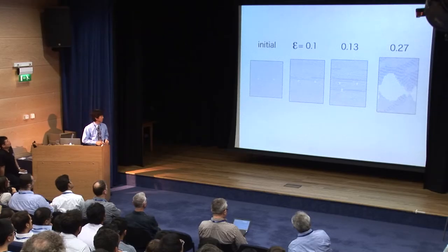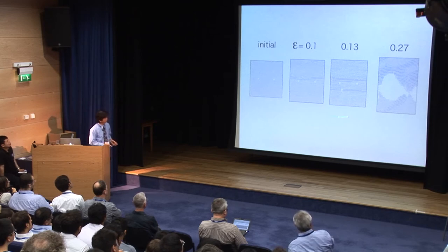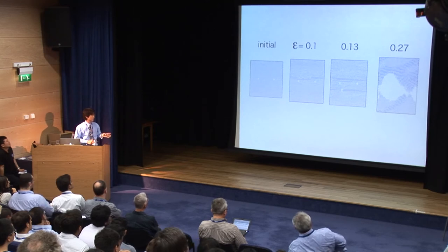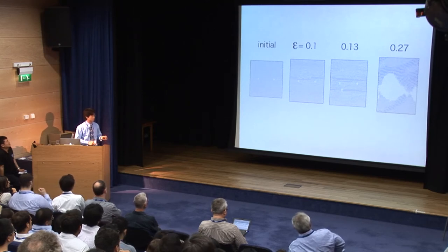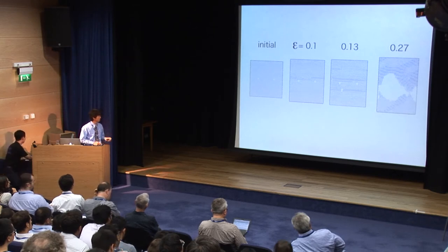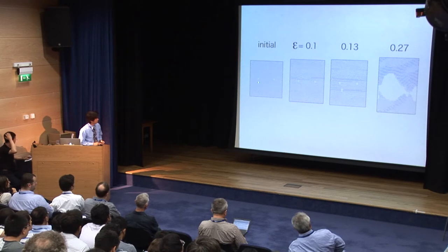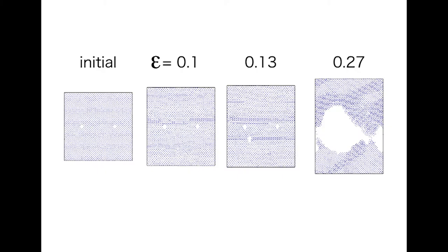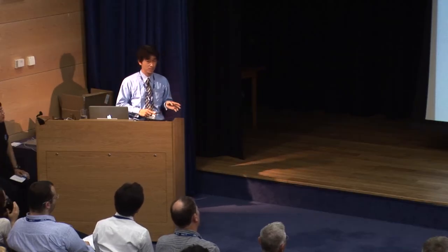This is a snapshot of the MD simulation of single crystal. And these figures are cross sections of the MD cell from the internal part of the thickness of 6 angstroms. At the initial stage, we can observe the vacancies. And the MD cell was stretched little by little. And some disordered area can be observed because of generation of dislocations.